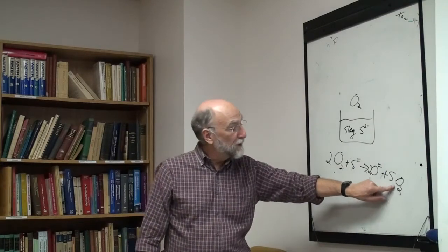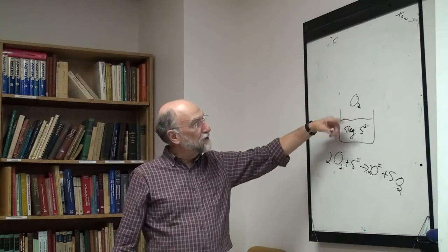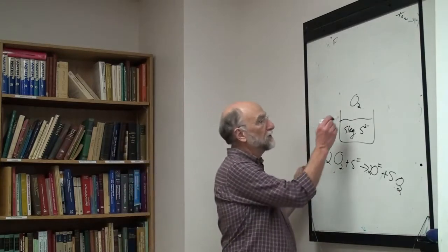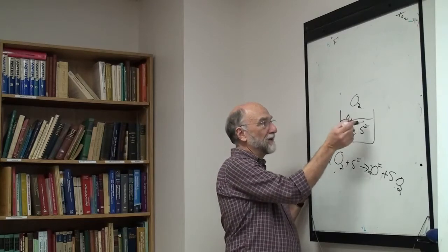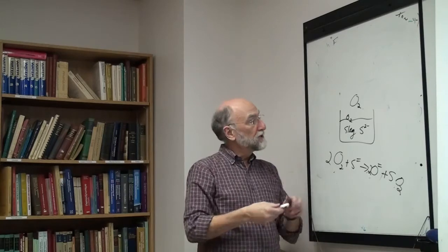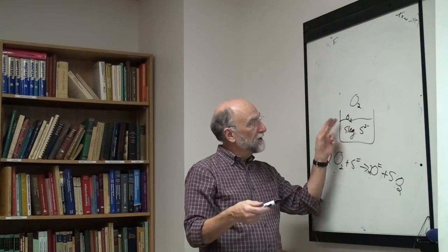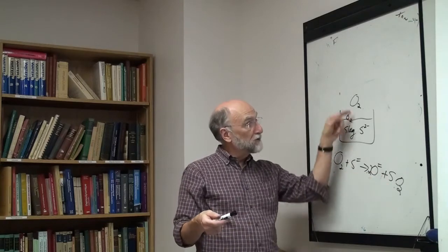When I did this with a slag, alumina, it's not just a reaction, but there's a charge transfer. You've got oxygen on the surface here, but the oxygen has to gain 2 electrons. There has to be a charge transfer between the oxygen and the sulfur. If you just had a slag, calcium-aluminosilica, an ionic conductor, the reaction went on, but it was quite slow.